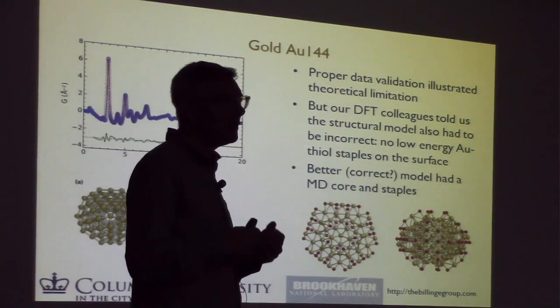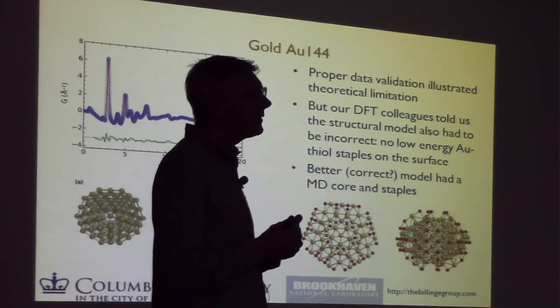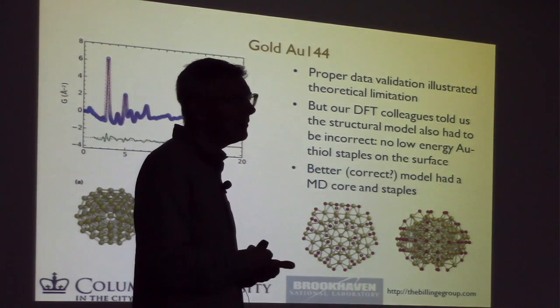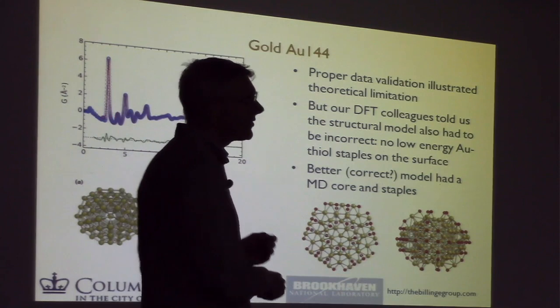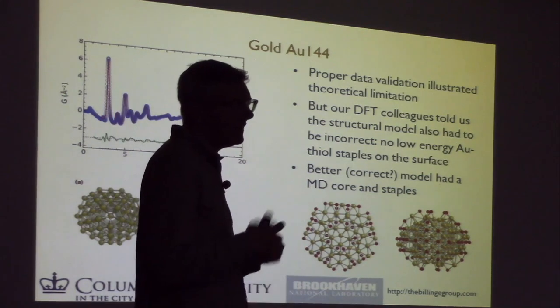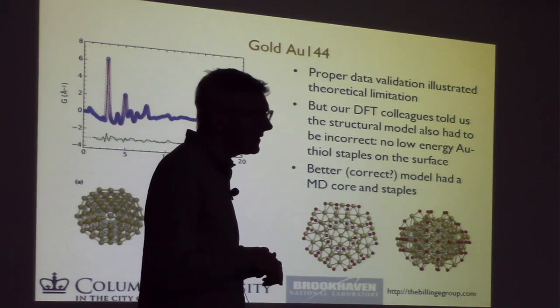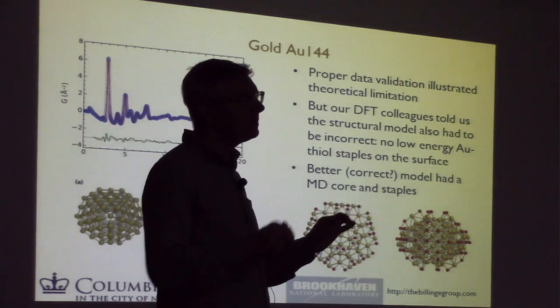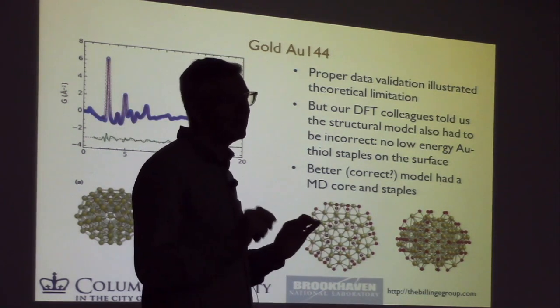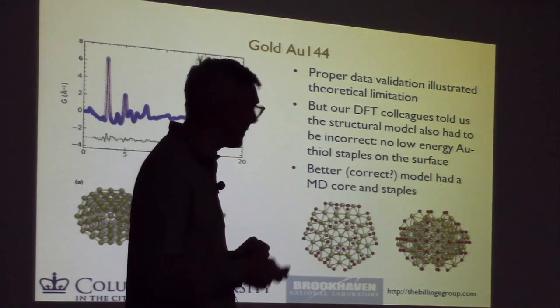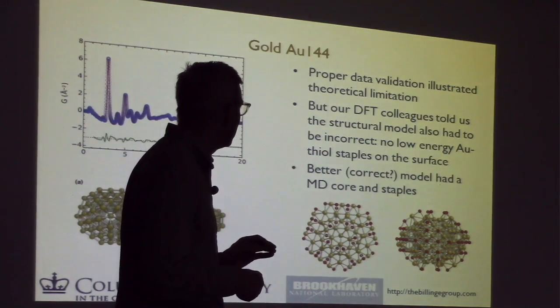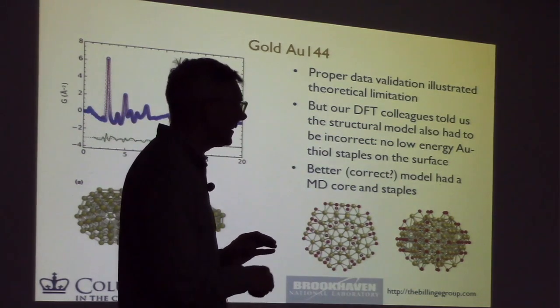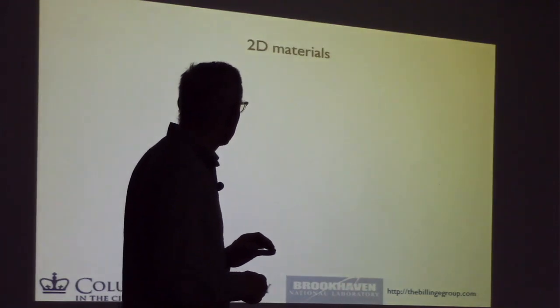In fact, the fit was really comparable. So what that's telling you is that the PDF data on its own was not enough to solve the structure. And the DFT on its own was not enough to solve the structure, but with the DFT plus the PDF together, we got a much better structure solution. But that's an example where we basically solved the structure.